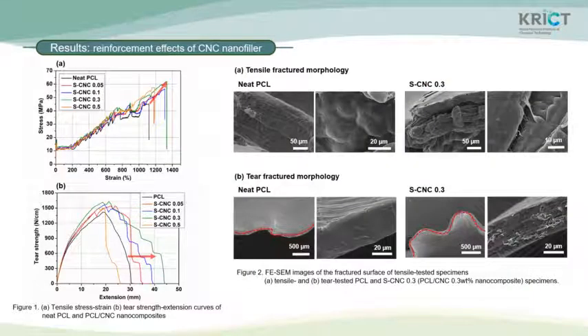To investigate nanofiller effects, we synthesized PCL and nanocomposites with various contents of CNCs by in situ polymerization. And you can see the tensile and tear test results in figure 1. Tensile and tear properties increased as the CNC content increases. However, over 0.5wt% of CNC, there was no reinforcement effect as a nanofiller. When 0.3wt% of CNC was applied, tensile and tear toughness was the best, which is almost 30% increased than the neat PCL. The stiff to tough tuning trend of PCL series was verified by observing the fracture morphologies of the tensile tested specimens of stiff PCL and tough PCL-CNC nanocomposite.